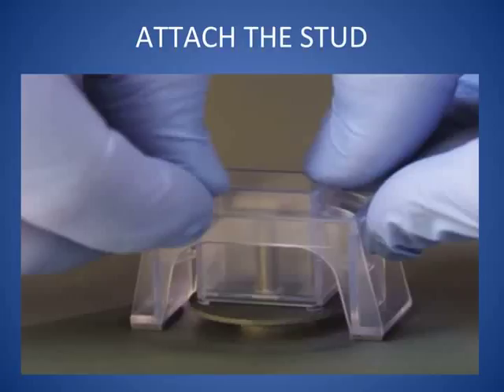And it's interesting on the click-bond thing that they've got this little feature: you put the right amount of pressure, it squeezes it down. It seems pretty good, but then in actual practice, you could have a temperature swing of, say, if you're in a shipbuilding atmosphere, somewhere around 45 degrees to 95 degrees. That same adhesive is going to have a much different viscosity at those different temperatures. So it's going to squeeze out differently. So in this application, it squeezes down and stops at about the right thickness. So it somewhat takes care of that. So even if you had different viscosities, it shouldn't vary too much.